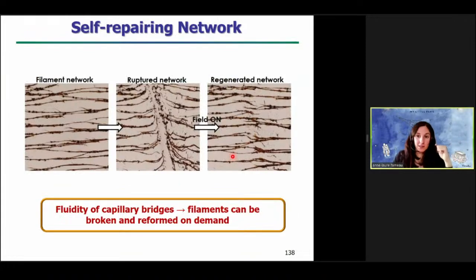But the property of this network is that it's a self-repairing network. That is to say, you have your initial network, you just cut your network, for example, as you can see here on this picture with a sharp stylus, and you have a ruptured network. But then by turning on the magnetic field, all the filaments can touch each other again. And when they touch each other again, they stick to each other again, and you have a regenerated network. And you can turn off the magnetic field and you recover your initial network. And this is really due to the fluidity again of the capillary bridges and their stickiness. The filaments can be really broken and reformed on demand.